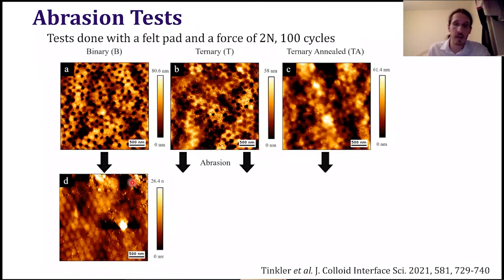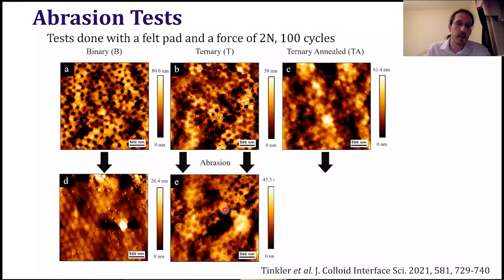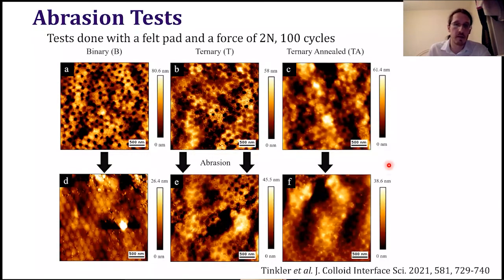If we have our ternary blend, we can still see the silica structure at the top. It's maybe slightly lower, but the structure is still there. So adding this second latex population is definitely increasing the abrasion resistance. And if we anneal the ternary blend, we have a similar result as well. So it looks like this could enhance the abrasion resistance.